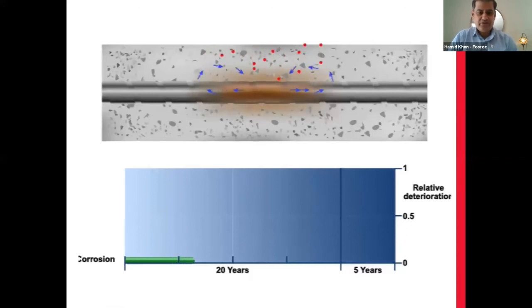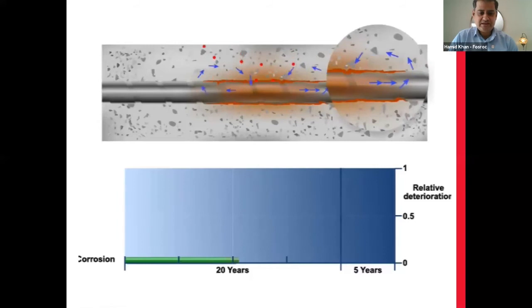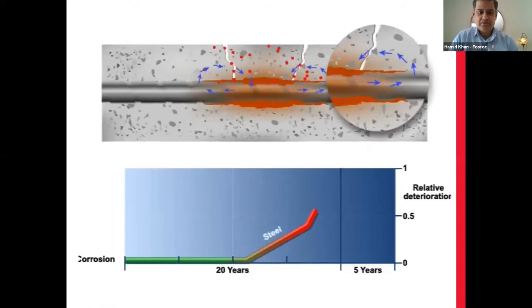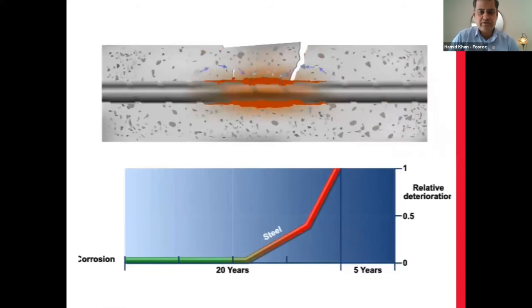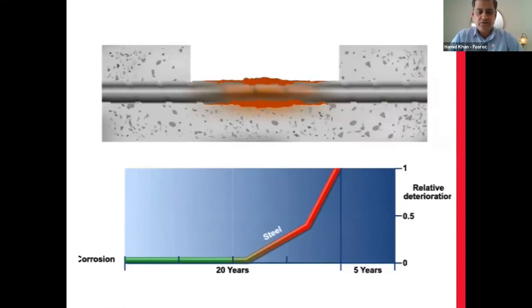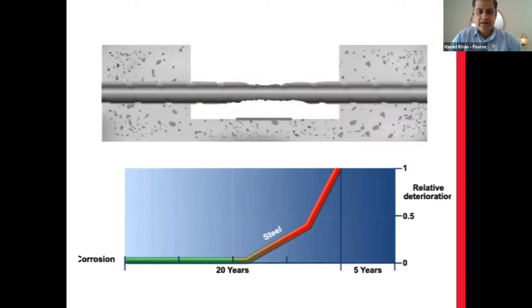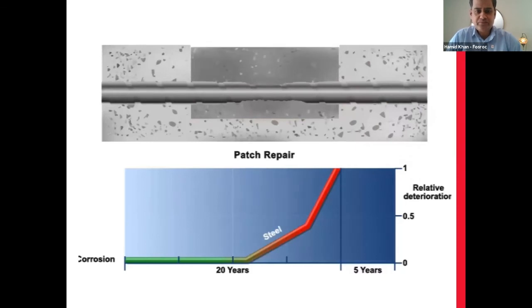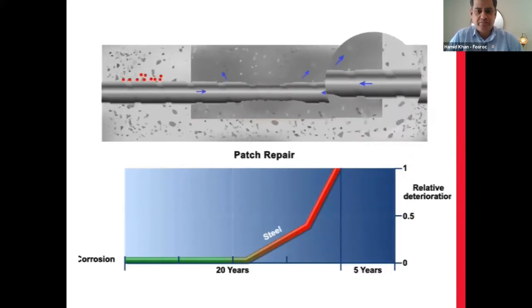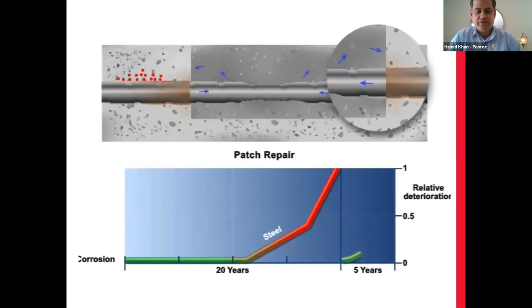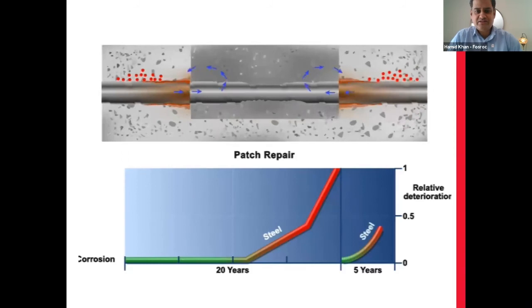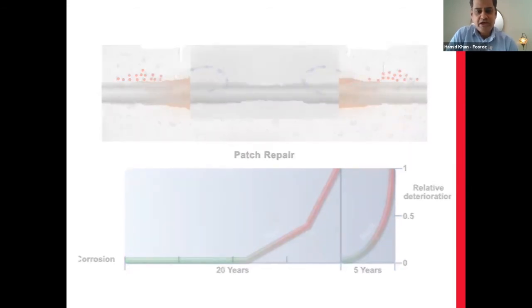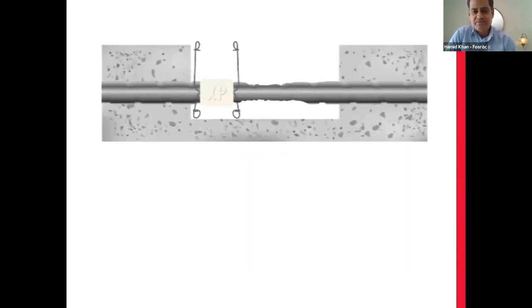So this is how the corrosion process initiates. It's green still, but suddenly the aging factor, or concrete quality, or cracks have started the corrosion process. And as a result, we can see loss of section for the steel. But what was done is that we removed that contaminated concrete completely and repaired it with a good patching repair mortar. And now we have reversed the process, and the adjacent areas that had lower chloride potential now have high chloride potential as compared to the repaired zone. And that has then caused that halo effect.